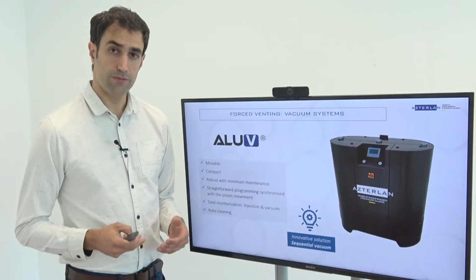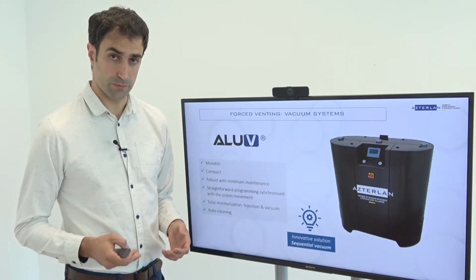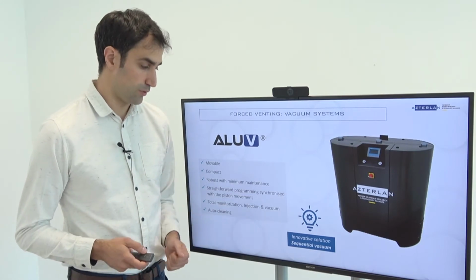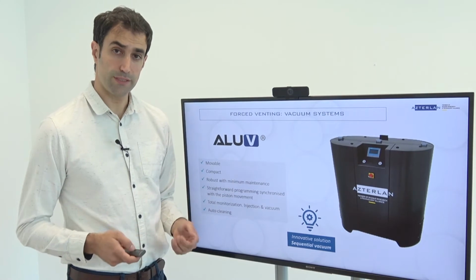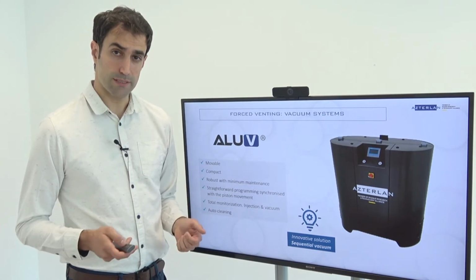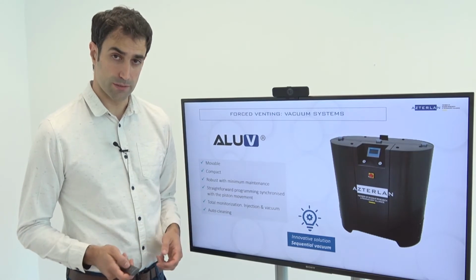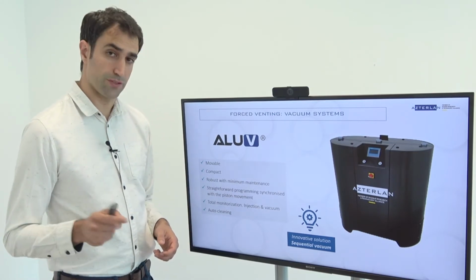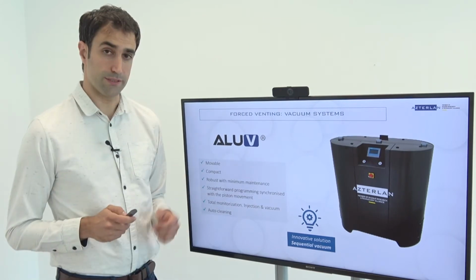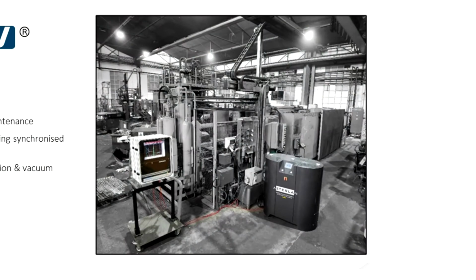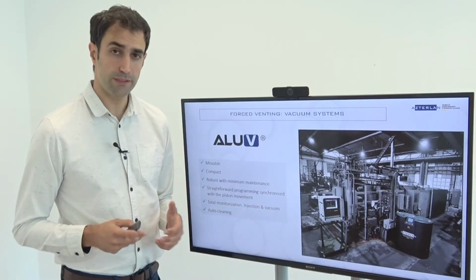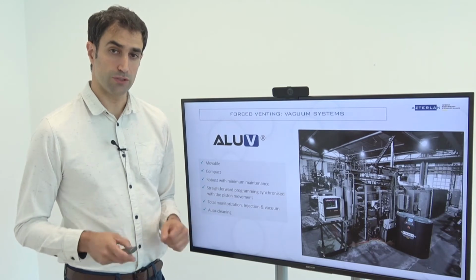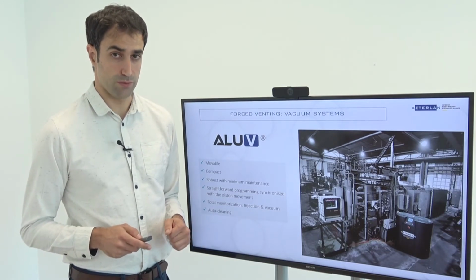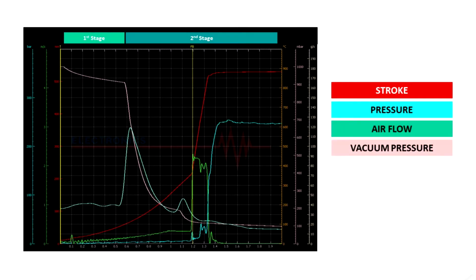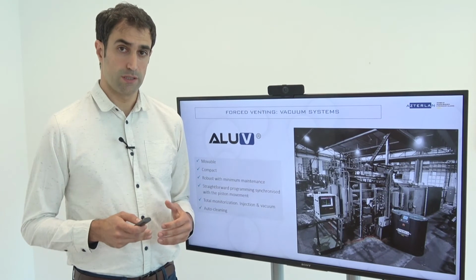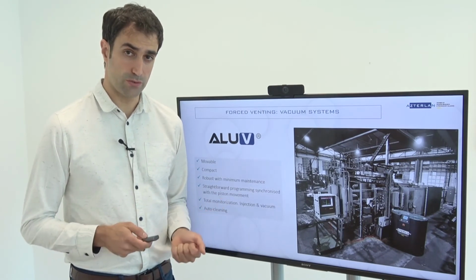Thus, at Azterlan, we have developed our own vacuum technology and equipment. It is presented as an innovative solution with a sequential vacuum capable of evacuating the gases from the mold in stages, which minimizes the sucking effect of a sudden vacuum step. I would like to remark on some of its features. It is movable, it is compact, let me say that it is the size of a thermoregulator, it is robust with minimum maintenance, but it is worth mentioning also the monitoring capacity of the most critical variables of the vacuum process. All of them are synchronized with the rest of the variables of the injection process, which allows us to check the adequate response of the vacuum system.